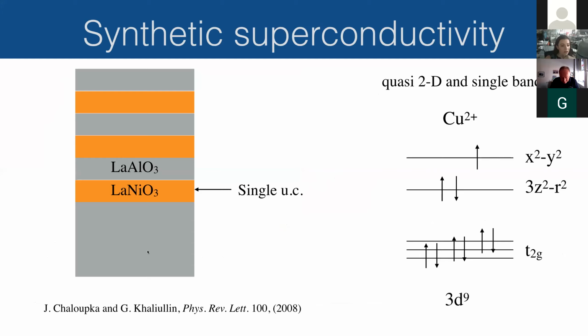So it was to say, okay, let's take very, very thin films of lanthanum nickelate and alternate them with something like lanthanum aluminate. They choose lanthanum aluminate because aluminium is not a transition metal. So basically there is a strong suppression of out of plane hopping of the electrons in this direction. You can imagine these gray layers as just being inert spacer layers essentially. So when you do this, you try to get single unit cells, alternating with spacer layers. The idea is that we could end up with an electronic structure that looks like the one of copper 2+ in the high temperature superconducting cuprates.